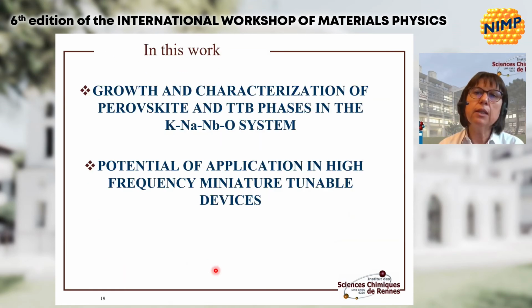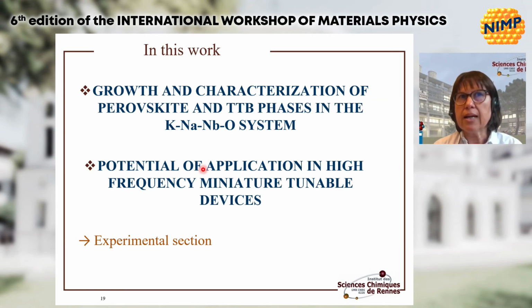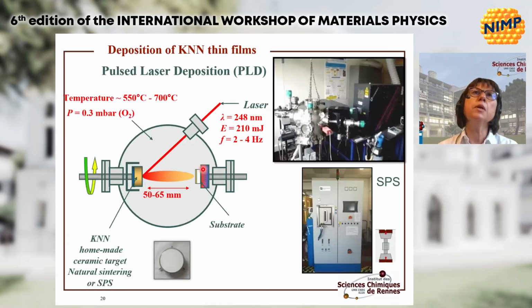So after this introduction on the KNN system and how to control the properties, I will first speak about the potassium-sodium niobate perovskite. After that, on the TTB. All the films have been deposited by pulsed laser deposition with homemade targets, sintered either by natural sintering or by SPS, spark plasma sintering. The films have been deposited in very standard conditions with an excimer laser, at a substrate temperature between 550 degrees and 700 degrees and a typical oxygen pressure of 0.3 millibar.